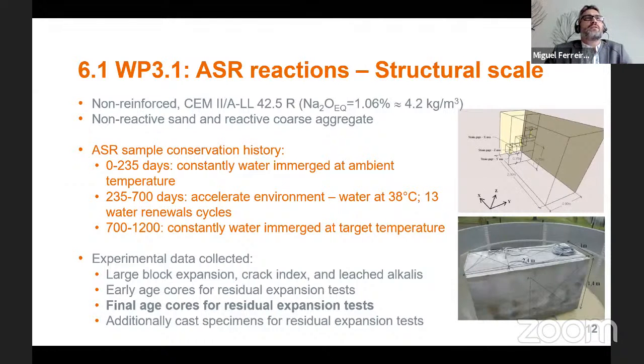And then we started the acceleration phase where we put it into a warm pool that you can see in the figure on the bottom on the right-hand side at 38 degrees. And this pool had 13 water renewal cycles. And during each cycle, we measured cracking in the wall, documented that kind of cracking in the wall. And then after those water renewal cycles, the block was again constantly immersed at 38 degrees without any more renewal.